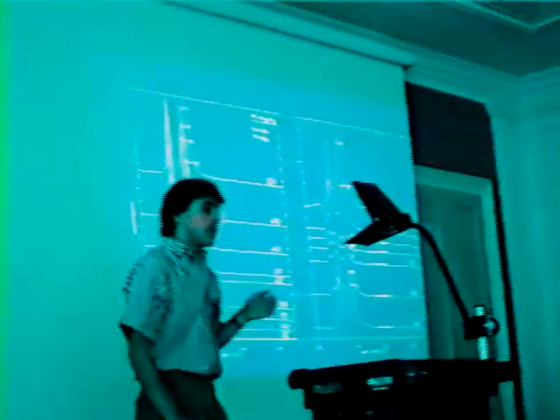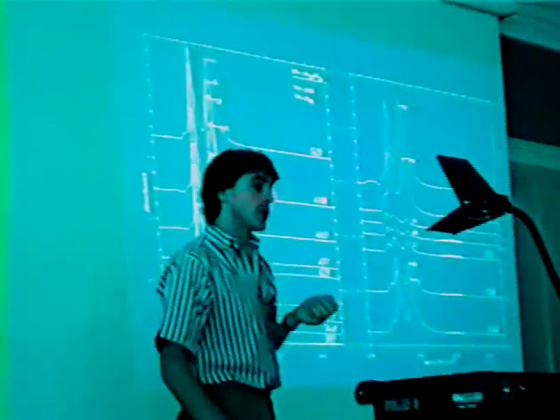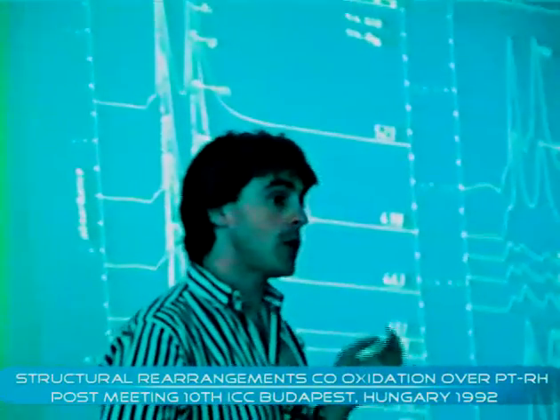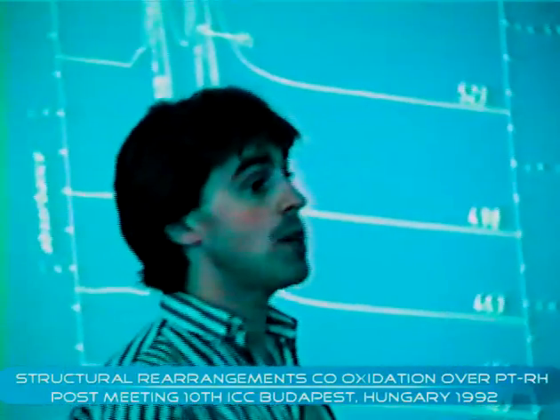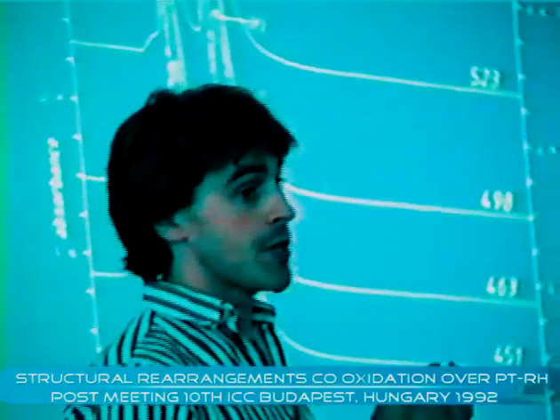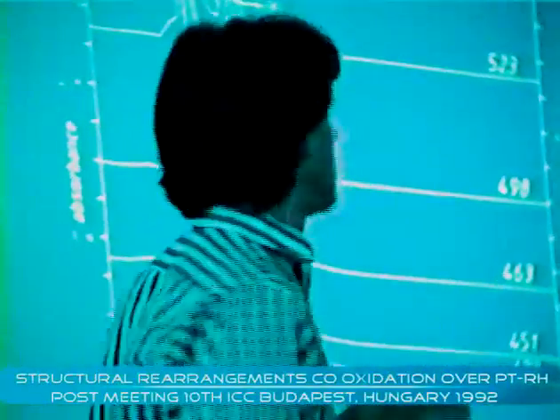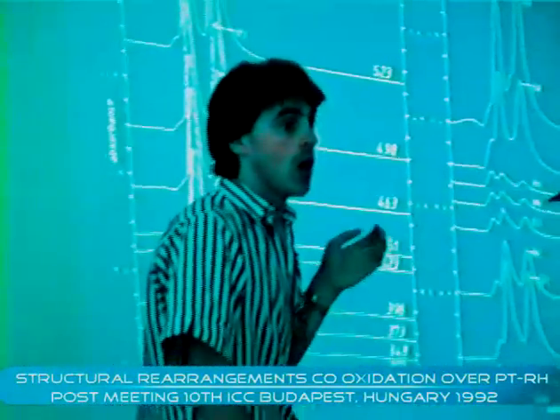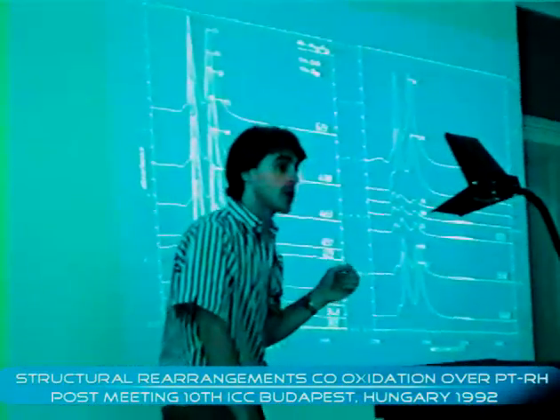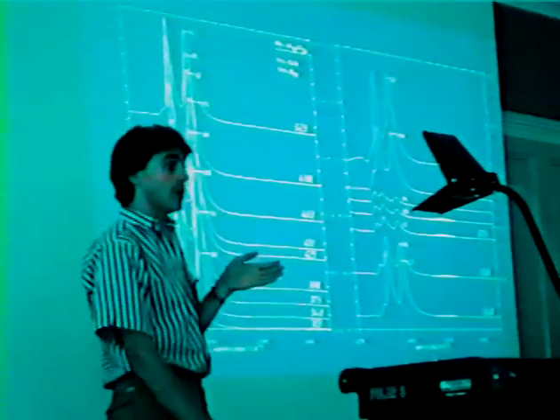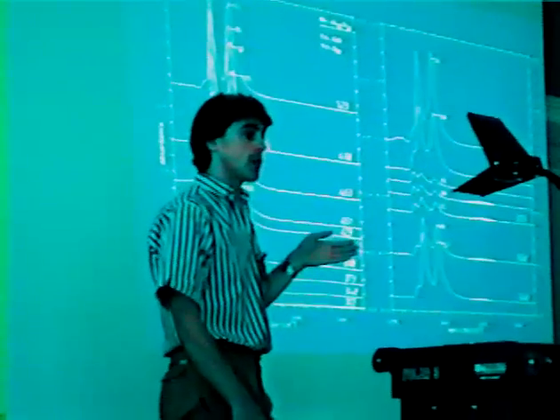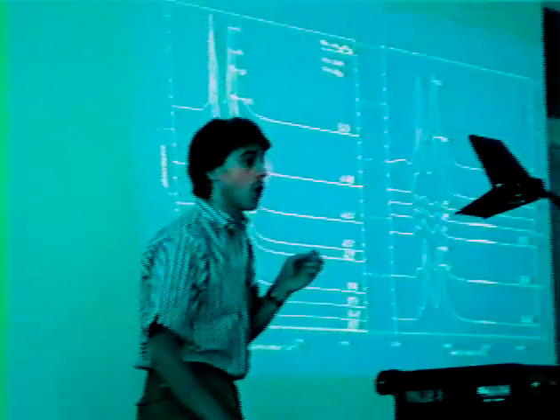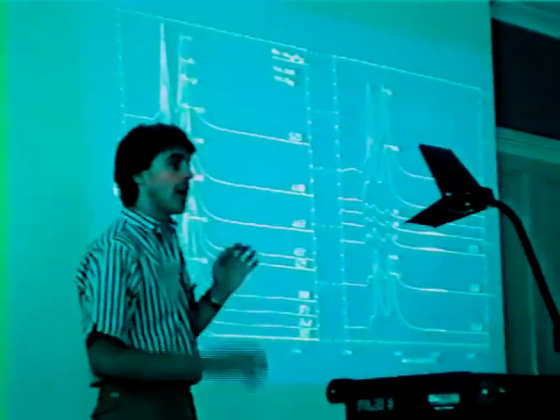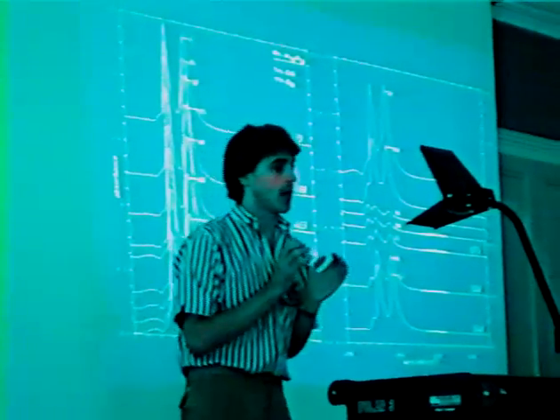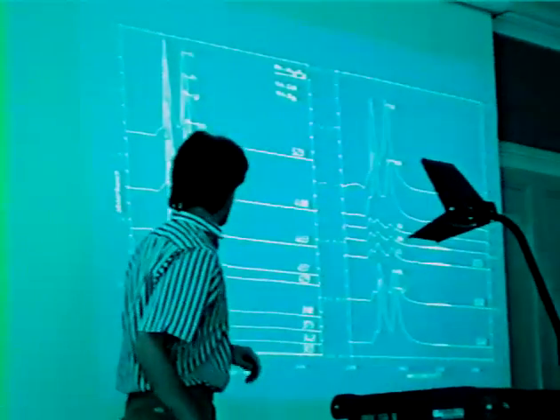Now, if we carry out this process in a flow of nitrogen containing CO and oxygen, in which CO is in excess, then essentially the same features will be observed. But because now the temperature which will dominate the control of the system will be the temperature at which complete conversion of oxygen takes place, there is now significant desorption of the gem dicarbonyl species. Therefore heating in CO and oxygen, in which CO is in excess, will be less effective in agglomerating the dicarbonyl species into a crystalline form.